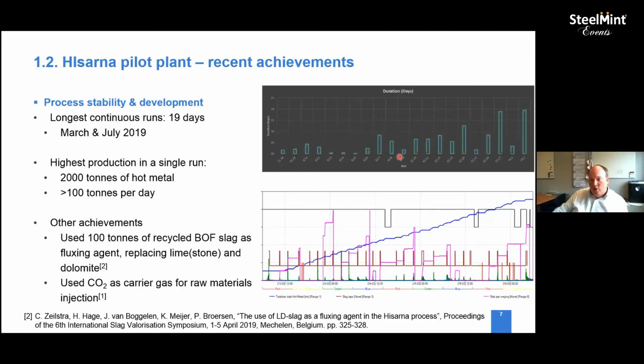Recently, later, we managed to create better, more stable equipment, but also to improve the process stability a little bit. And we managed to run for nearly a week, 10 days, that sort of order. And then early 2019, we managed to grasp some of the key issues that resulted in the process instabilities that we had been suffering from. And that immediately resulted in much longer runs of 19 days, where the process stability has not been an issue at all. And for these long runs we start running into equipment stability issues again. So the longest runs we've done, March and July 2019, were 19 days each.